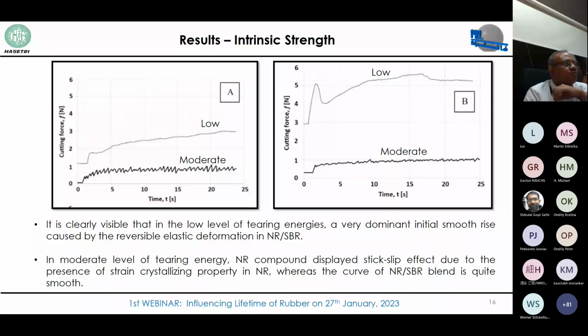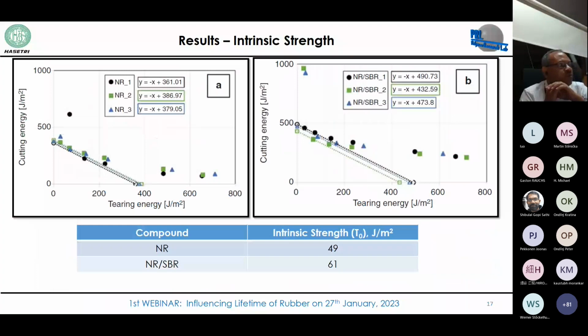After this, cutting energy versus tearing energy is plotted. The detailed explanation has already been given in the previous work and can also be found in the literature, so I'm not going to discuss how these things are measured. However, this is the curve for our natural rubber and natural rubber SBR compounds. Intrinsic strength for the natural rubber based compound was 49 joule per meter square, whereas for the NR-SBR it was about 61. So the addition of 60 parts of SBR has helped in achieving higher intrinsic strength. The threshold limit has increased, and it was also shown in the previous work that natural rubber is about 40, and if you go for BR, it will be much higher, almost double.